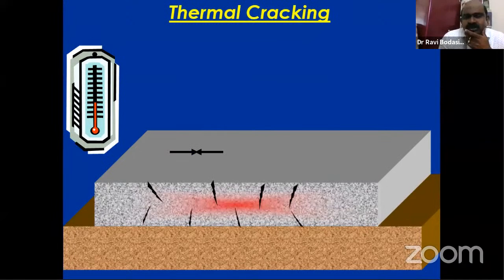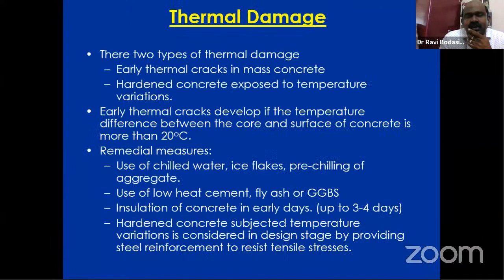So the temperatures while placing the concrete for huge massive pours, then definitely the thermal effects, which is the exothermic and endothermic reactions, occur in the massive pours and definitely will affect the concrete. This can be controlled while pouring the concrete by considering the temperature of the concrete and by cooling the aggregates and placing temperature. All these things will help to control the thermal damage, which is going to have a major effect on the durability of the structure.